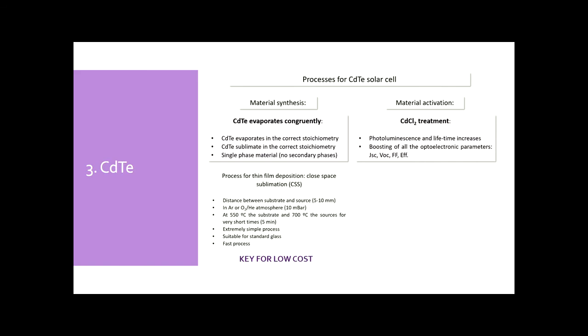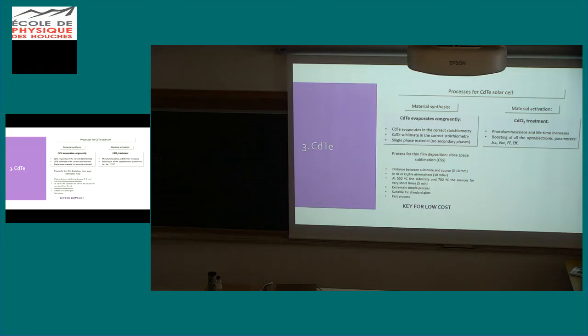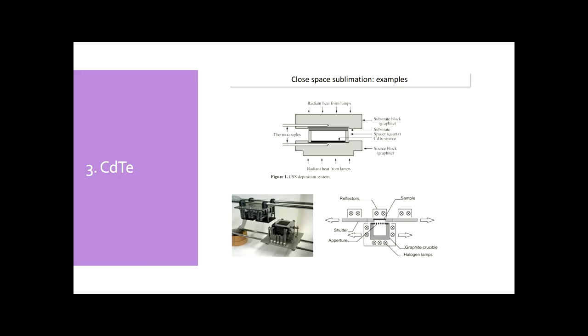But then you need a material activation process. Cadmium telluride by itself, if grown by this evaporation process, is not as good as if you activate it with cadmium chloride. This is a further thermal treatment, and these are the conditions that you can find in the literature. This cadmium chloride treatment allows for a very high efficiency and was one of the main discoveries to improve the efficiency in cadmium telluride.